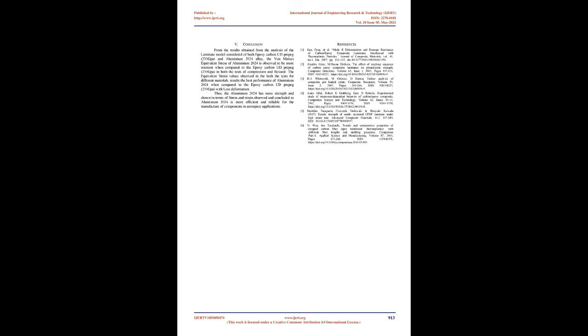From the results obtained from the analysis of the laminate model considered of both epoxy carbon UD prepreg, 230 GPa, and aluminium 2024 alloy, the von Mises equivalent stress of aluminium 2024 is observed to be more resistant when compared to the epoxy carbon UD prepreg, 230 GPa, in both the tests of compression and flexural. The equivalent strain values observed in both the tests for different materials, results the best performance of aluminium 2024 when compared to the epoxy carbon UD prepreg, 230 GPa, with less deformation. Thus, the aluminium 2024 has more strength and shown in terms of stress and strain observed and concluded as aluminium 2024 is more efficient and reliable for the manufacture of components in aerospace applications.